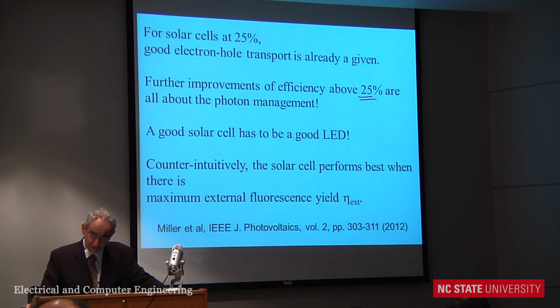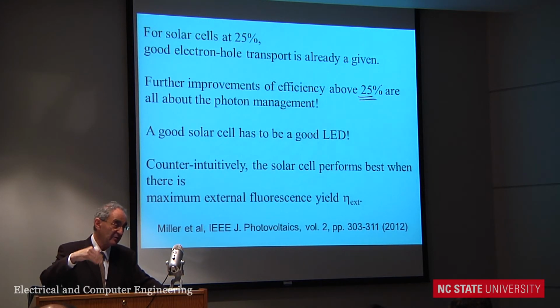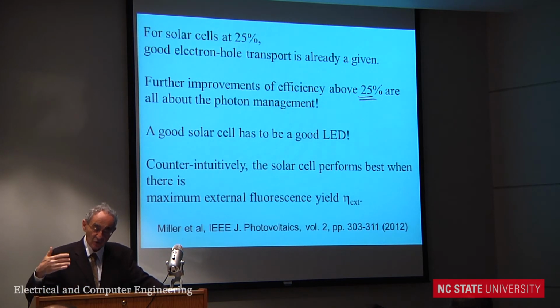I can tell you a little bit about the history of this. They started getting these higher voltages, and I told them to keep improving that rear mirror. So they had a 96% reflectivity mirror, and they broke the world record. And then 6 months later, with the same material, the mirror was improved to 97% reflectivity, and they broke their own record. And then they improved the mirror to 98% reflectivity, and that's the current world record, and they broke their own record again. So nothing was changed about the material. It was all about the photon management that made that possible.